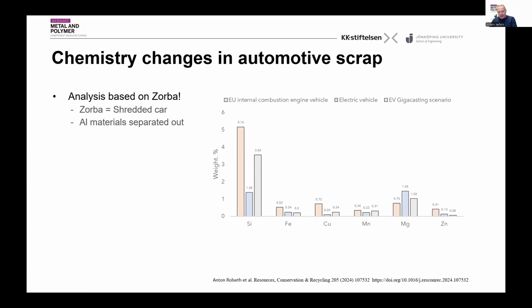Now, the saving grace here is the study by Anton Rolseth, where we did some scenario planning and looked at what happens if we now add the mega castings, and that means you add the rear floor to the cars, or the front or some other elements, battery cases and such. Those alloys do not have a huge amount of silicon. They typically have like 7 or 8% silicon. So the consequence of the rear floor being added and replacing steel components means that the average composition of the scrap coming from Zorba would end up about 3.5% silicon.